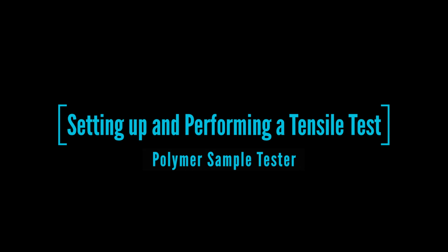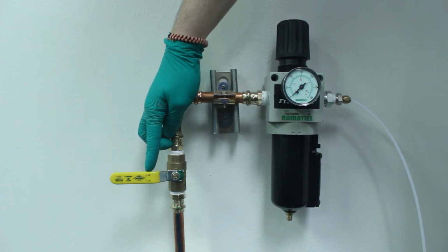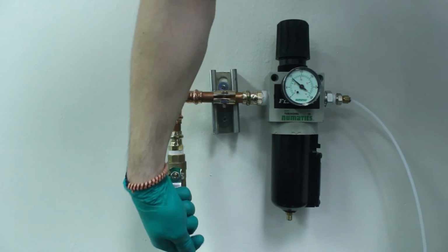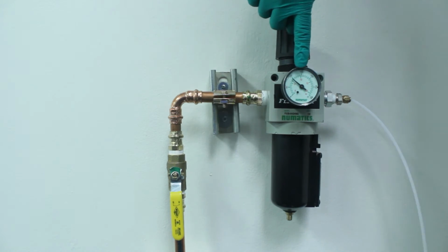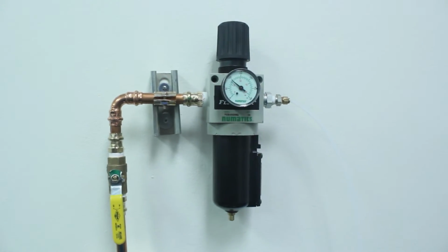Next, we'll go over how to set up and perform a tensile test on the polymer sample tester, which varies just slightly from the metal tester. Open the valve for compressed air located on the wall to the left of the tensile tester so that it shows about 100 psi.